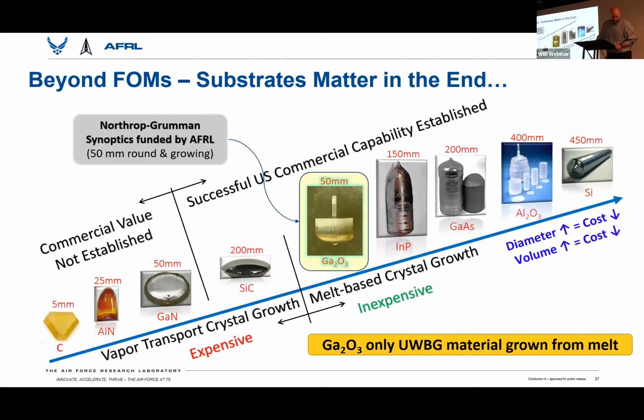One thing that people talk about when they're talking about device engineering is bounds or figures of merit, but the problem goes a little bit deeper than that. We can say that we want to get to low R-on and high breakdown, but one thing that people don't consider when they're benchmarking that way is cost. This is one of the main things that we see as promising for gallium oxide, like I mentioned before: growing from a melt makes production a lot cheaper. You can see here all the way to the left, that would be diamond and silicon carbide. Those have to be grown through what's called vapor transport, where the tools are expensive and the process is complicated, which makes the product expensive. So we see this as a major win for gallium oxide. We think that the other problems can be engineered out. Go ahead.